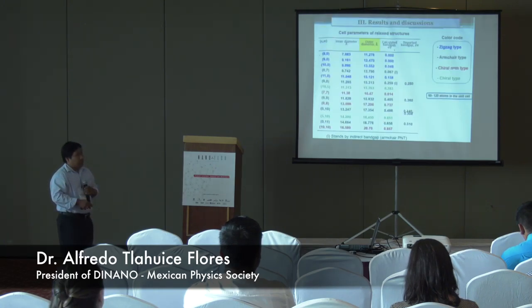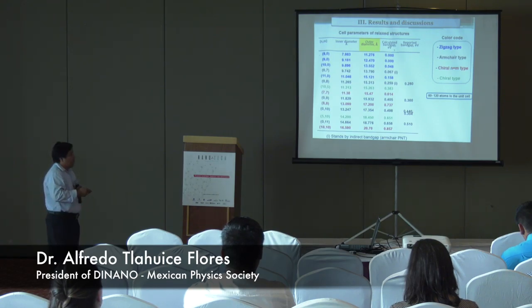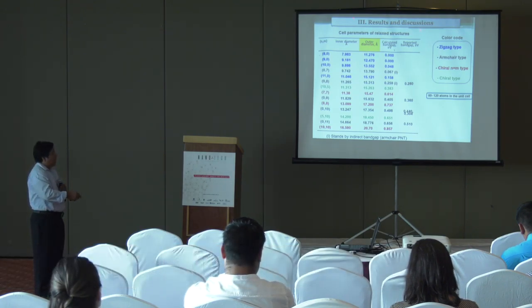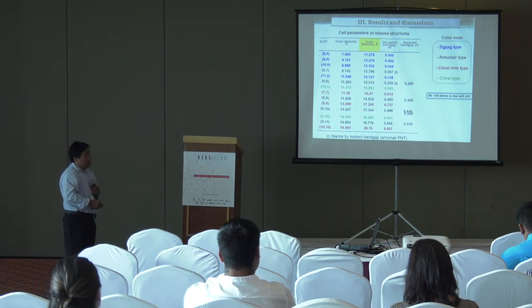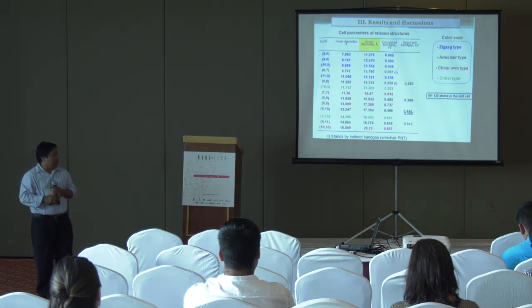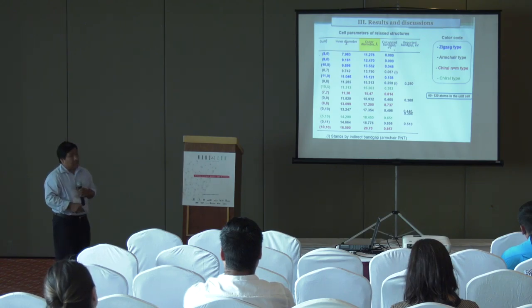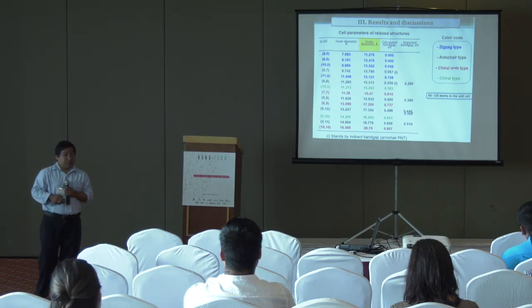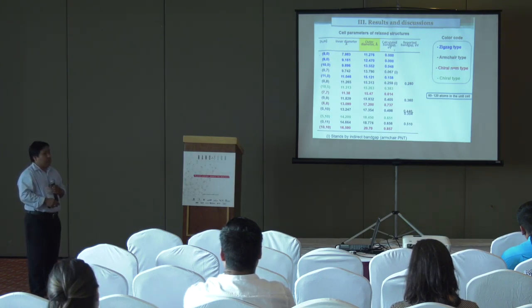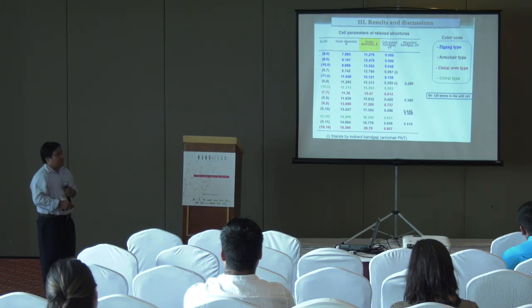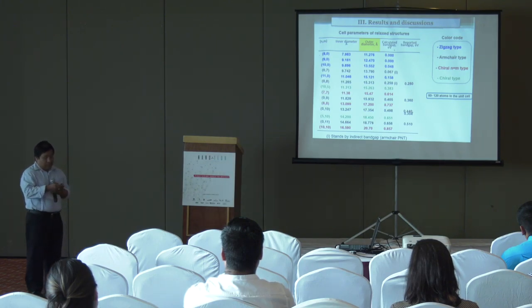And the small ones will be in the inner part of the cylinder. Another paper mentioned that these band gap values are comprised in a range from 0.10 to 0.61 eV. So our study considered 14 structures: four zigzag nanotubes, five armchair, and five chiral structures. The most important parameter in this calculation is the outer diameter, ranging from 11.3 to 20.7 Angstroms. The number of atoms inside the unit cell goes from 60 to 120 atoms, so you need a workstation with 25 to 60 cores and more than 100 gigabytes for the calculation.